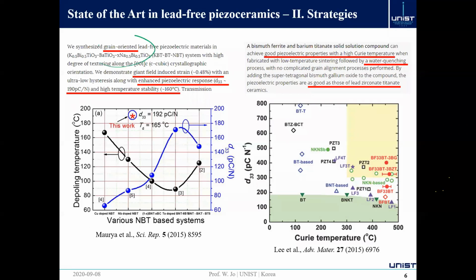So with grain orientation, even though the achieved value here is not that high, one interesting thing is that if you apply this templated grain growth technique, even though the d33 is not that high, the strain seems to be enhanced quite a lot. I'll talk later about the interrelationship between strain and the piezoelectric coefficient, but templated grain growth seems to be very useful if you consider high strain materials.